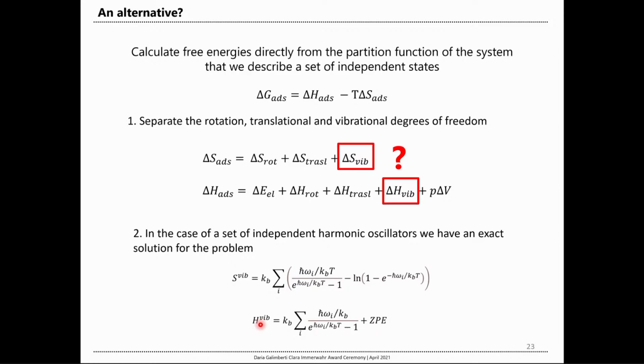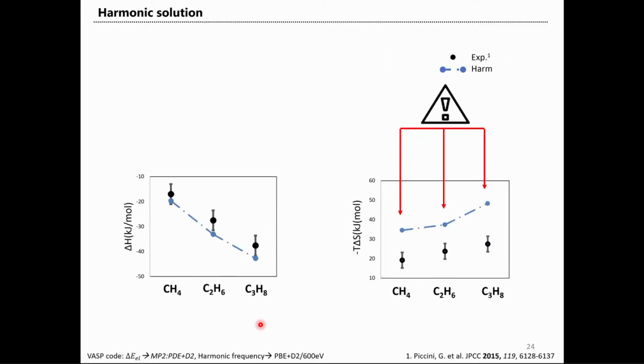But if you try to make this calculation, and we come back to our example, this is what happens. So if you look at the enthalpy term here, and these black dots are the experimental values, you can see that, yes, the harmonic approximation worked quite well. We are near the chemical accuracy. We are not so far from our experiment, so we are happy. But if we look at the entropic term, we are off.